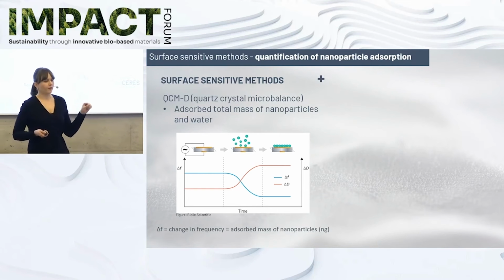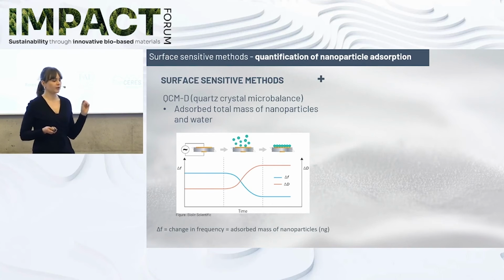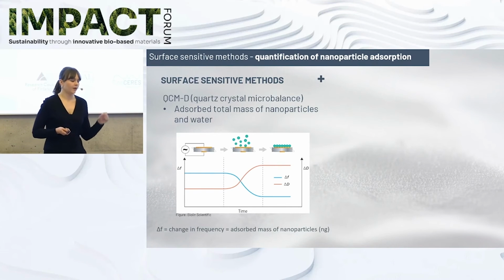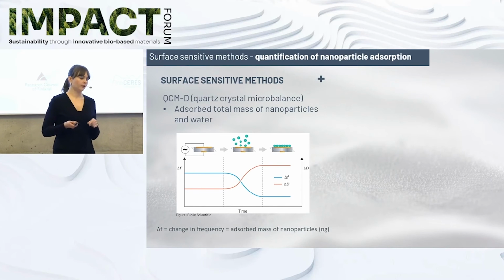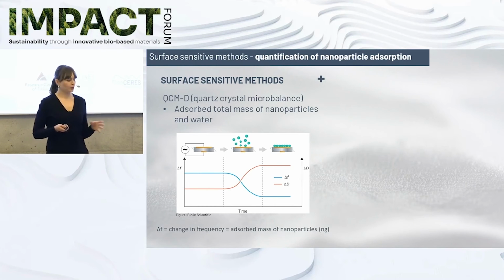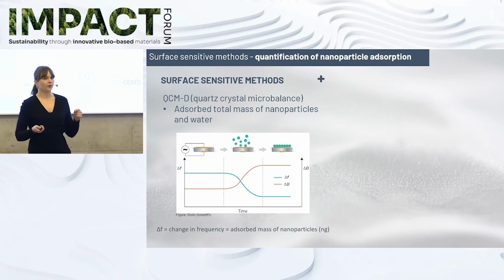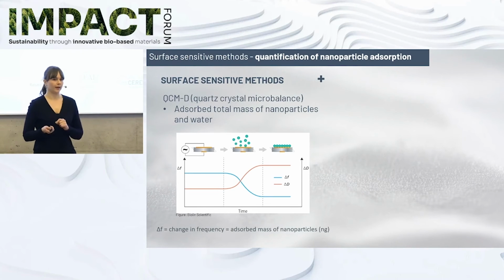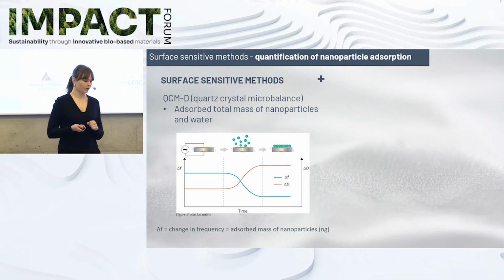So here we have combined these surface-sensitive methods with cellulose, and we have used this QCMD, which is basically a very sensitive balance that is able to measure the adsorbed mass of these nanoparticles on different surfaces. So basically you inject the nanoparticle solutions through the chamber, and then you measure the change in frequency. And the change in frequency is then the same as the adsorbed mass of the nanoparticles. So you can really calculate small amounts from low concentrations.